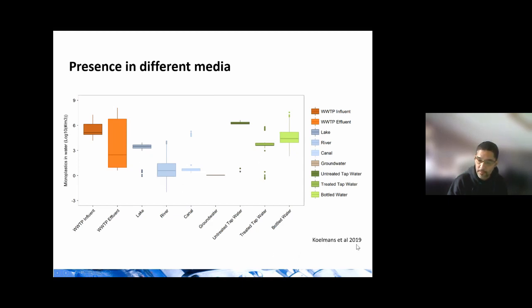This is work published in 2019 by Koelmans. You can see that they range between 10 to the power of 3 and 10 to the power of 8 concentration per cubic meter, and you can see as well that the variability is quite large, depending on which kind of sample you get, from wastewater treatment plant effluents to bottled water.